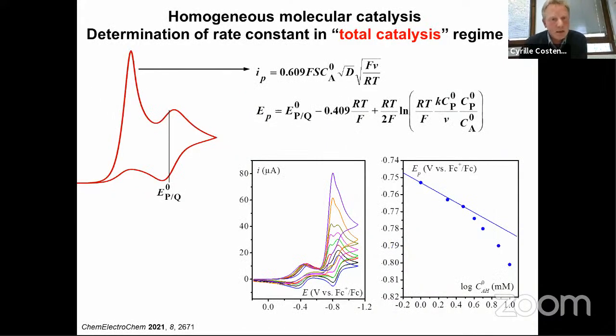And in that case, as you can see, there is no more information from the plateau, from the current here, because the current here is controlled by diffusion of the substrate. So the current peak is just proportional to the concentration of the substrate and the square root of the diffusion coefficient of the substrate.